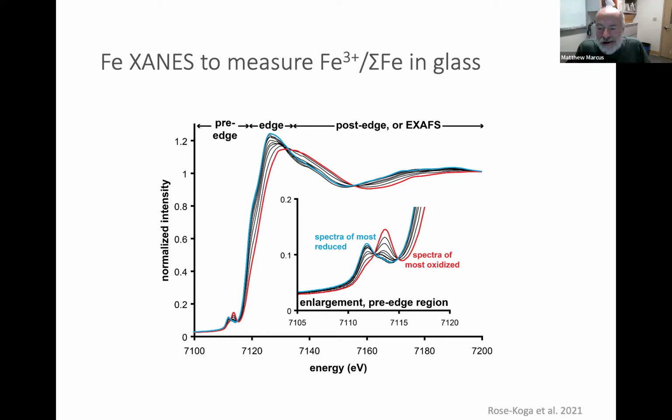Yeah, still might be worthwhile to give a test where you run nitrogen over the surface, see what happens. Yeah, I'll say yes. That's an interesting suggestion, Matthew. Right. So one of the complicating things for beam damage here is that the water in these glasses is at a few weight percent, and so it's partially dissociated. So that complicates what is being reduced and driven away. Right. So iron may be coordinated partially to OH, for instance. Exactly. Yeah.